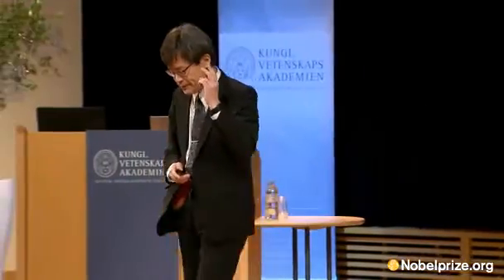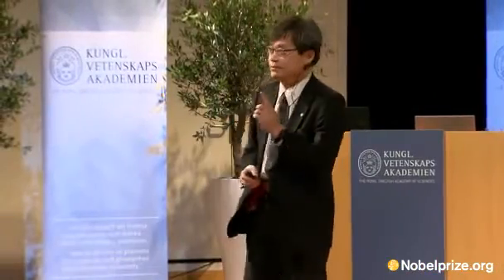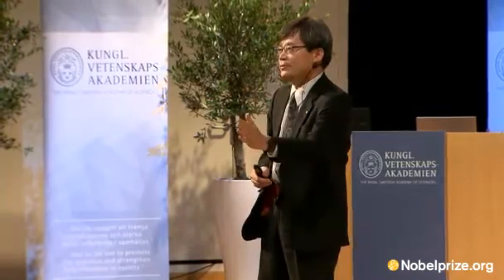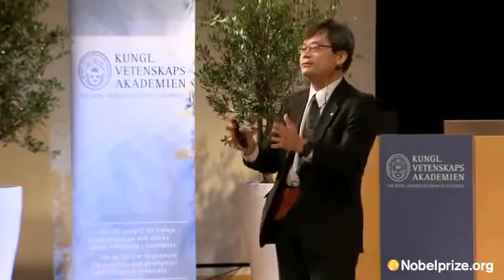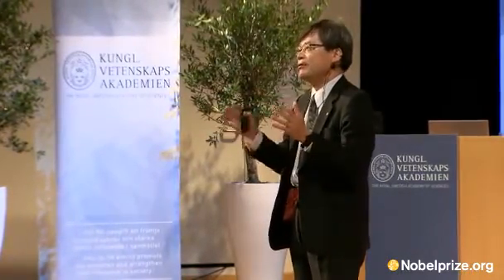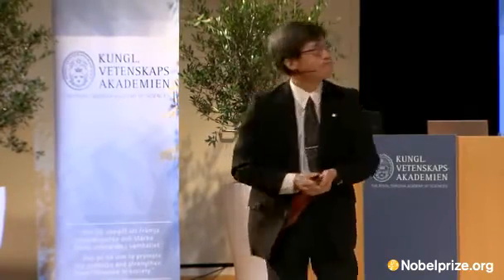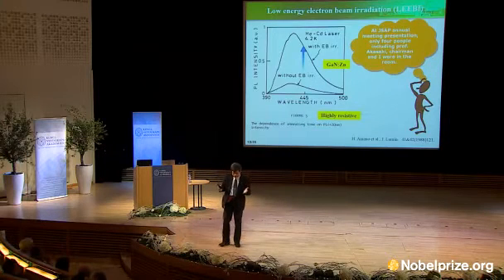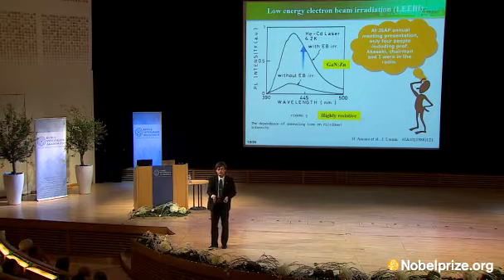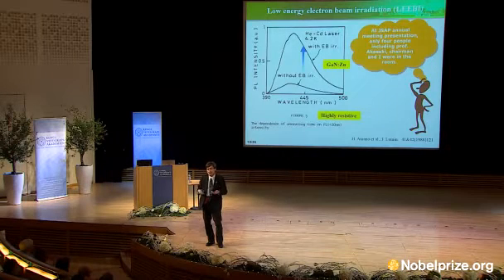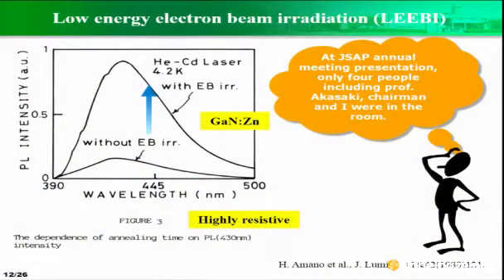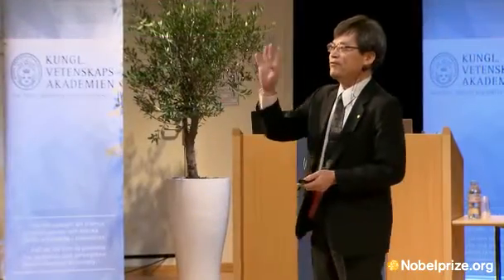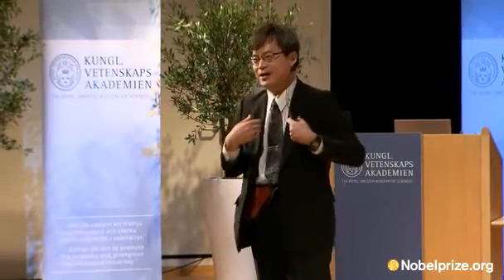Then, of course, our next target was to realize p-type gallium nitride. From 1985 to 1988, I concentrated on growing zinc-doped gallium nitride, but all the samples showed highly resistive or n-type. When I measured the photoluminescence at cryogenic temperature, I observed a very narrow excitonic peak. So I was excited and tried to present at the Japan Society for Applied Physics annual meeting held at Nagoya University. And when I entered the room, I was surprised that only 4 people, including Professor Akasaki, the chairman, and I, were in the room.